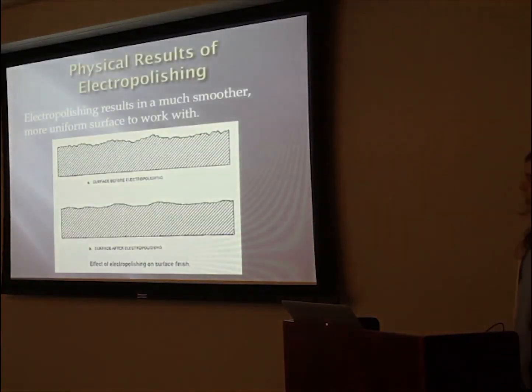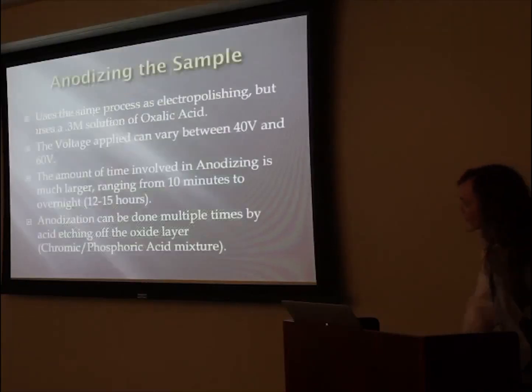So here's a cross-section of kind of what that looks like. You end up having some kind of bumps and ridges inside of here along with the general lay of the topography of it. What the electropolishing actually does is it reduces that grittiness. You still get the overall topography of the surface here, but it makes it much less bumpy. It's more smooth and ideal for making these pores that we want to create here.